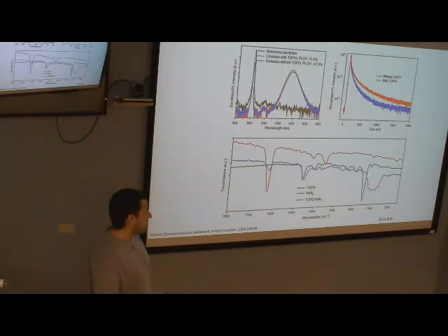And in the perovskite structure, they're trying to conclude that the TOPO did have a successful binding to the perovskite structure due to this broad peak that we see here. As you can see, in the undoped or clean version there was no peak visible there, but in the doped version there was. So you can conclude that there was a successful ligand binding between the two.